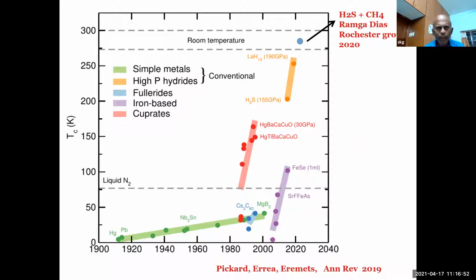But there are exciting developments in very recent time with hydrogen-rich materials, because Wigner pointed out many years ago that if you take solid hydrogen and pressurize it, it will become a metal at high pressure. But it has not become a metal so far. But then theorists got excited, particularly Ashcroft, that if you look carefully at that metal, because the phonon frequencies are very high, the Tc will hit room temperature. So it started the game of hydrogen-rich materials. And we now have real temperatures reaching room temperature in hydrogen-rich materials, so-called carbonaceous and sulfur materials. I will come to it later. It's not far from Buffalo, the Rochester group, Ranga Dias and company, they have found this. So this is a new branch, which is very exciting. We will discuss it a little bit later.